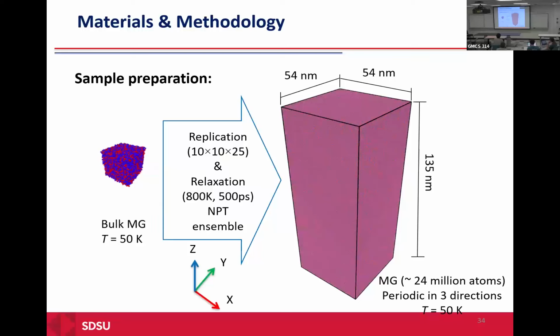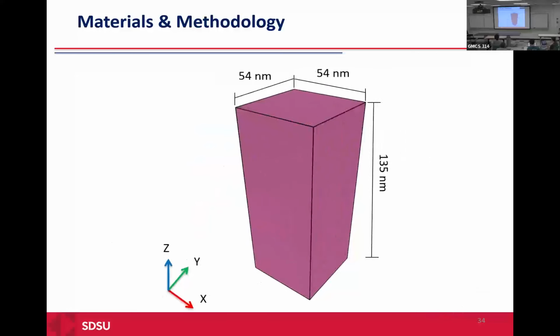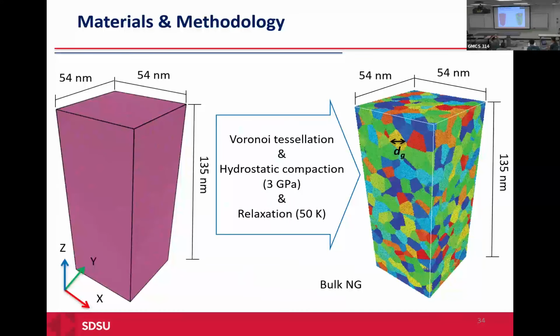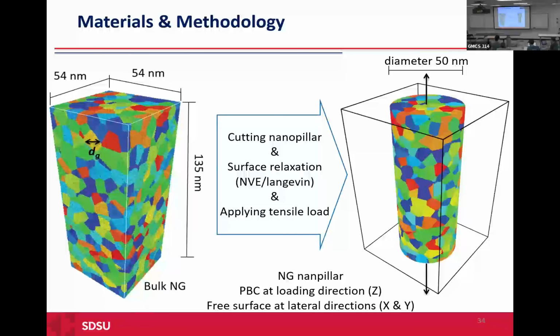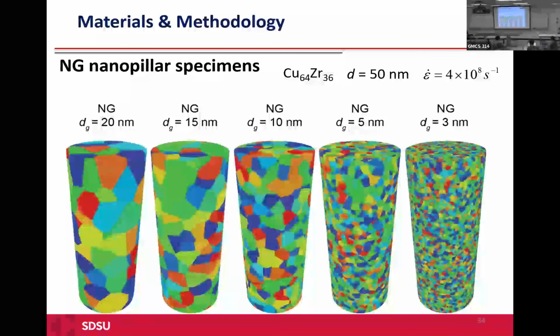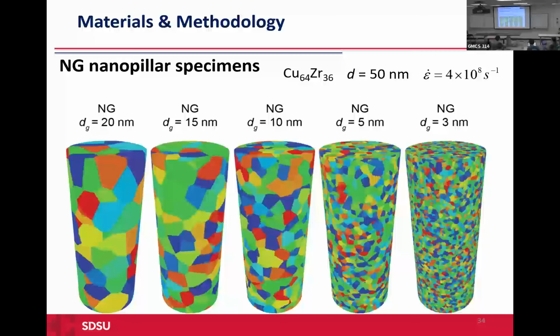And then we replicate those materials and relax them and apply some pressure to make the sample size that we are looking for, and then use hydrostatic compression to remove any pores that we have in the microstructure. Then we had the structure of the nanoglass. Then we cut the nanopillar from this nanoglass. We have nanopillars with different grain sizes, and we applied uniaxial loading to the nanopillars to see how the nanopillars with different grain sizes would deform under uniaxial loading.